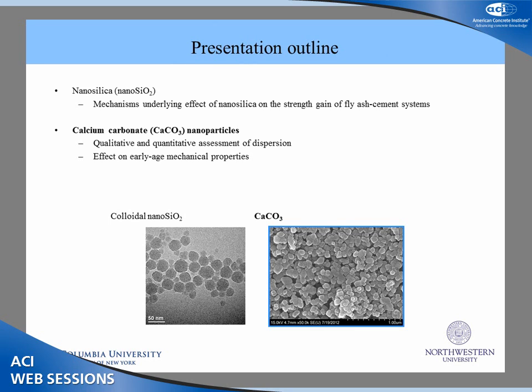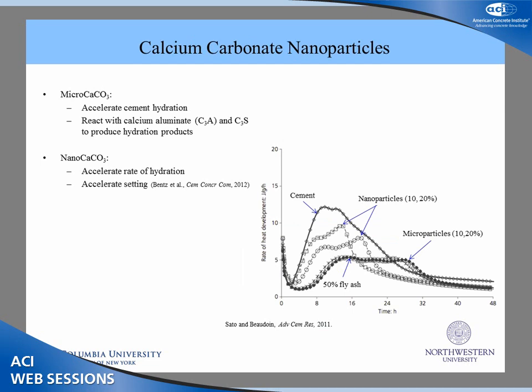And again, here we really focused on the issue of dispersion, because with nanoparticles, we're seeing these effects because they're nano size, and this leads to the increase in specific surface area that allows them to participate in all these effects like seeding, increased reactivity, filler effect. But if they're not properly dispersed, then we won't be taking advantage of the benefits. So here we're really focused on the qualitative and quantitative assessment of dispersion, and then looked at the effect on the early age properties.